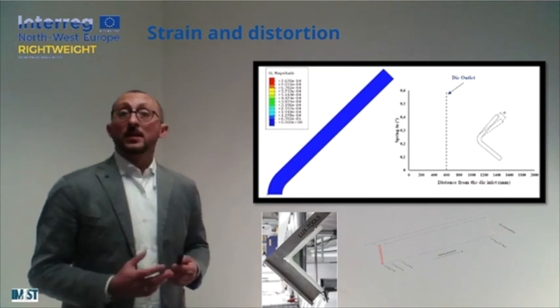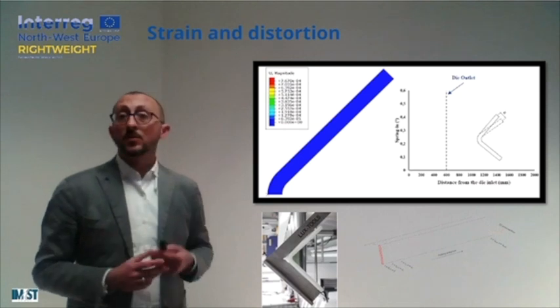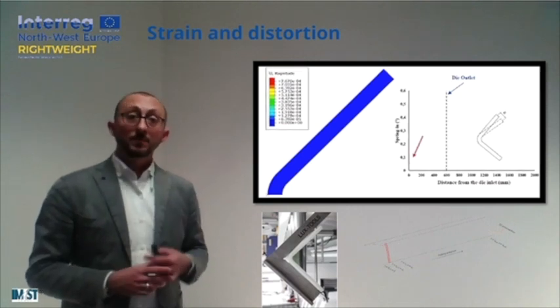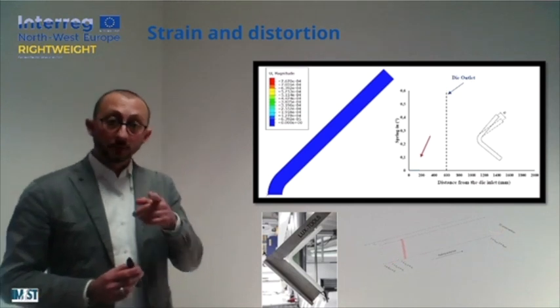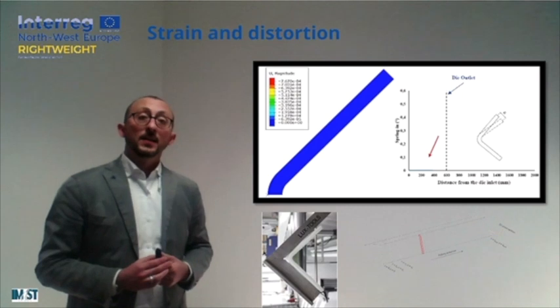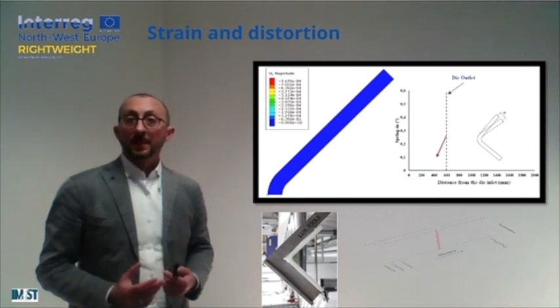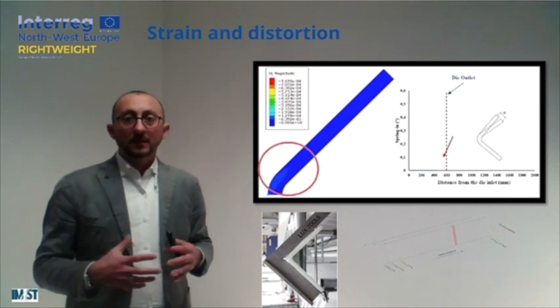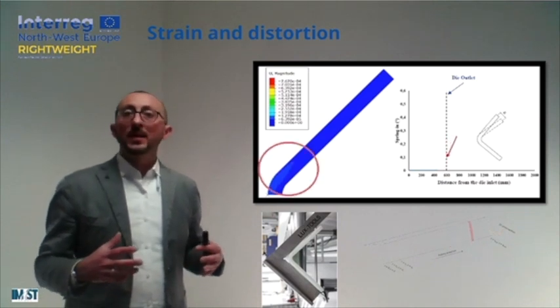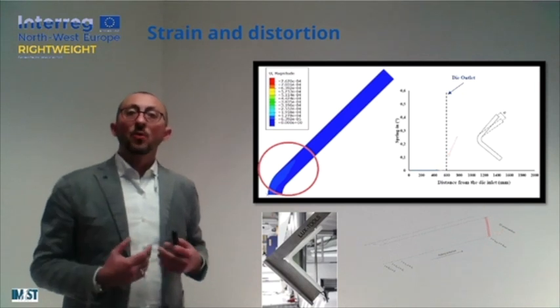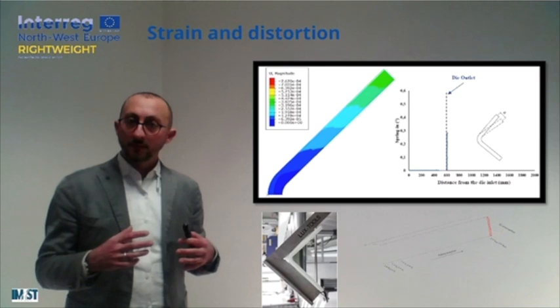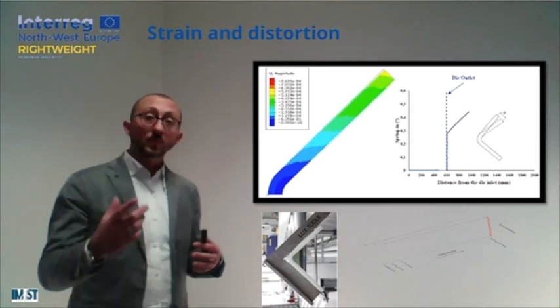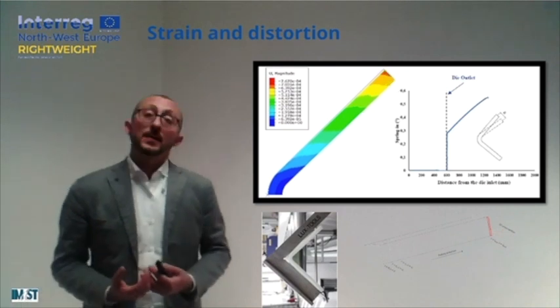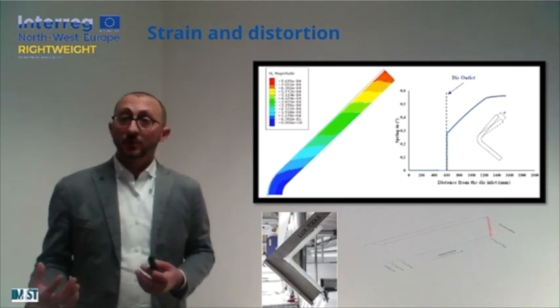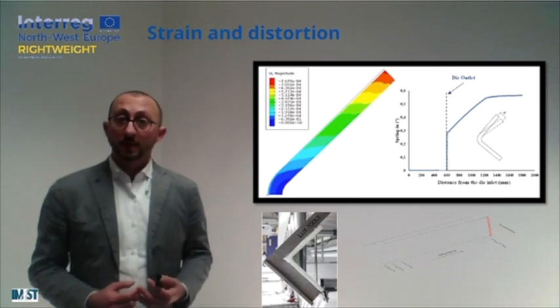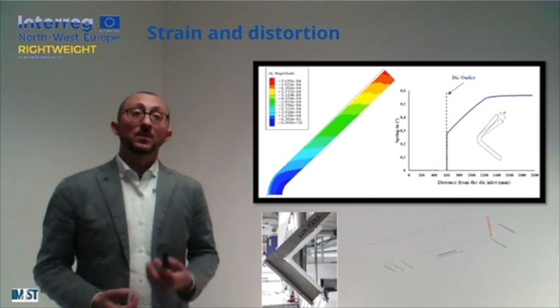Once again, the virtual simulation can give us an idea of what is going on inside the material when we are traveling inside the die. So if you take a look at the red arrows there, it indicates the position inside the die. When we are inside the die, the material is heated, it tends to expand, but it is constrained by the cavity. But as soon as the material goes out of the die and this constraining is not there anymore, all the internal stresses that are coming from the thermal expansion or the chemical shrinkage will be released in terms of distortion.